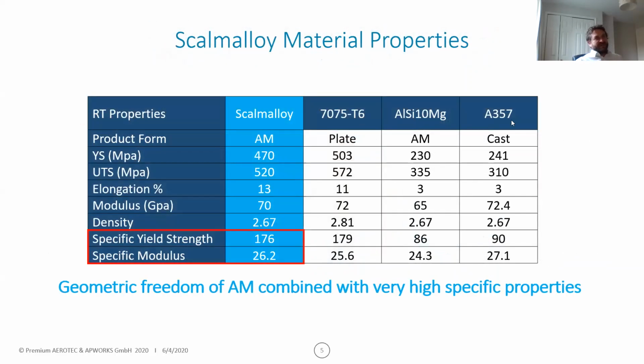To compare the material properties just to a few alloys, so I just picked a few. So 7075 T6 is a kind of fairly high strength plate material. You can see very high UTS. But also high density. Scalmalloy has a reasonable quantity of magnesium in the alloy, and this is bringing the density down a little bit. So it has the same density as aluminium silicon 10 or A357 if you're familiar with casting. But it has strength values, and particularly yield strength, which is of course very important for design, which is really up there in the range of a 7000 series alloy, and with ductility that is up there in the range of the good direction for a 7000 series alloy.